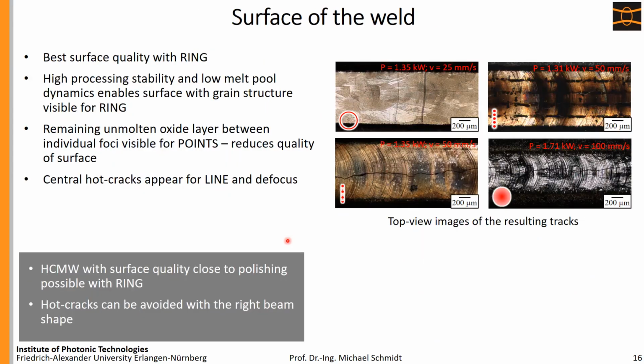Something that might also be of interest is the surface after the weld that we had a look at. Again, the best surface quality we reached was with the ring shape, whereas with the others, like the dotted line, we have reduced surface quality, because you can always see small transitions into keyholing where the middle of the dots were. With the line, you can see cracks that appear in the middle, as well as with the defocus, which has to do with the shape of the area where you have solidification.